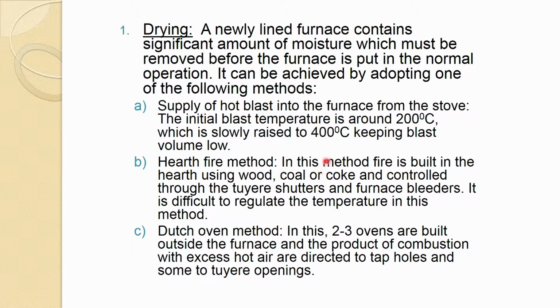In this one, at the bottom of the hearth you use this carbonaceous material and burn it by using controlled air through the tuyere shutters and furnace bleeders. But the only problem is that it is a bit difficult to control the temperature in the furnace. But if stoves are not there, this is one of the methods one can adopt to remove the moisture and heat up the furnace in the starting.